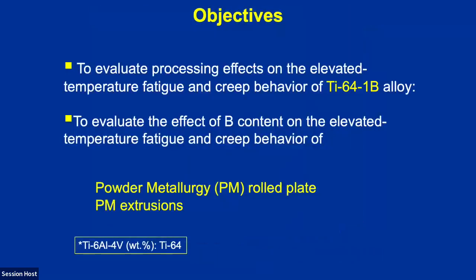In this work that we did, Wei Chen evaluated a bunch of different compositions and different processing techniques, and a couple of those were based on powder metallurgy. He wanted to understand the processing effects on the elevated temperature fatigue and creep behavior to see if we could use this at elevated temperatures, and to evaluate the amount of boron that could be used, to find what the optimal content would be for the elevated temperature creep and fatigue behavior.